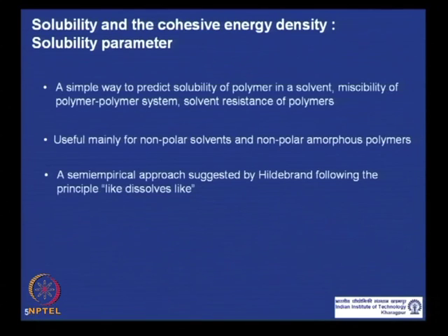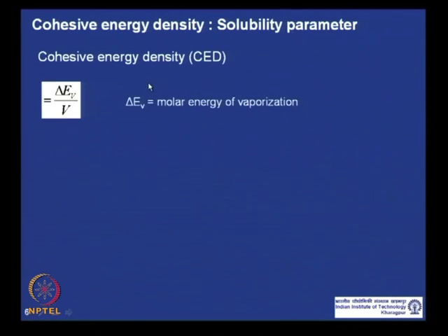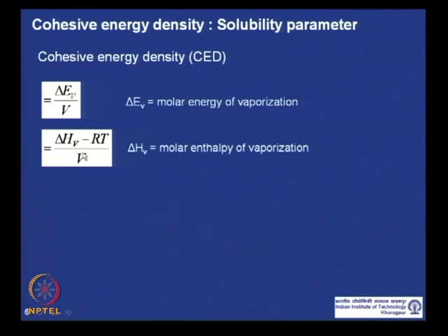It's basically a semi-empirical approach, as suggested by Hildebrand, following the principle of like dissolves like. This means that polymers which have a similar structure or similar interaction behavior with the solvent will dissolve in that solvent. Quantitatively, the cohesive energy density is defined by this, where delta E_V is the molar energy of vaporization. It can be written by this expression also, where delta H_V is the molar enthalpy of vaporization, and V is the molar volume of the substance.